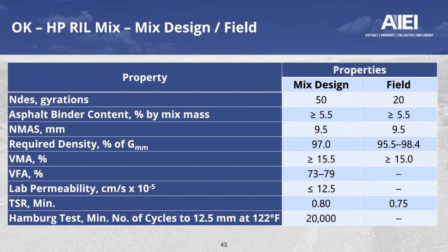In terms of mix design, again, a 50 gyration mixture, keeping the binder content not quite as high. They have a minimum of 5.5% on their 9.5 millimeter mixes. They are designing to a 3% air void at percentage of GMM. Their VMA is the 15.5, as we saw in Ohio as well. VFA is 73 to 79.